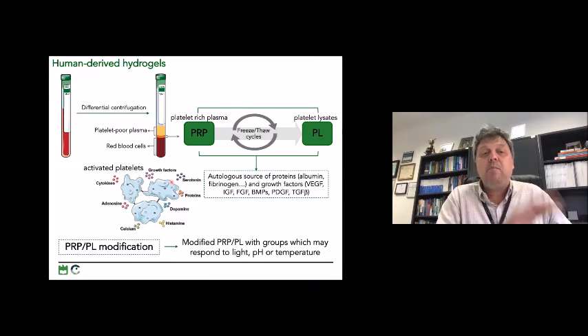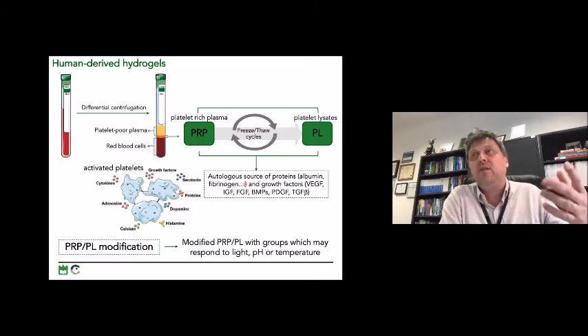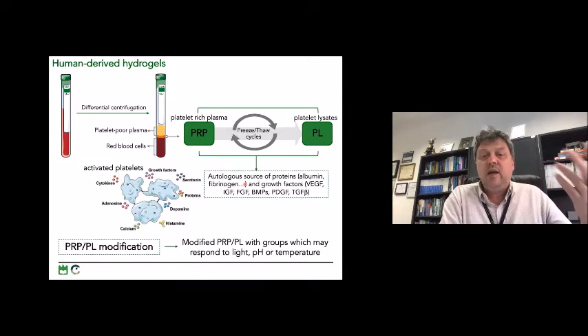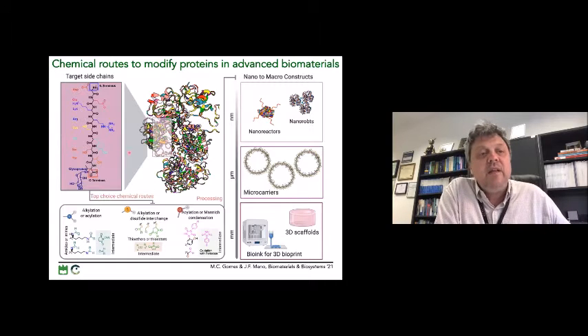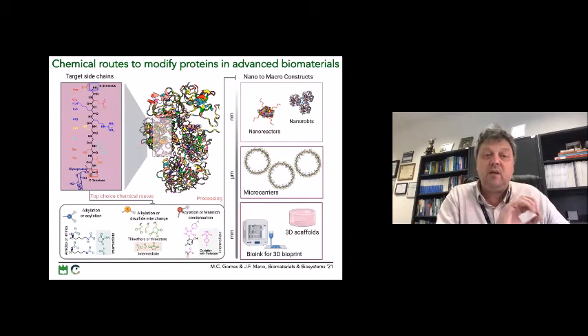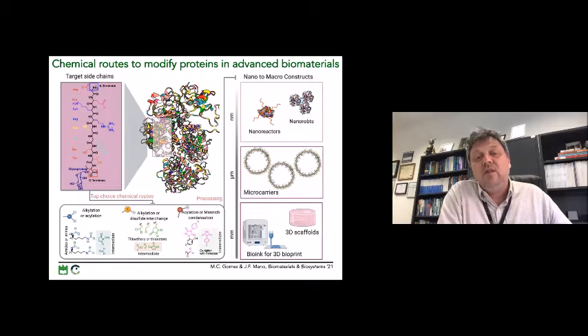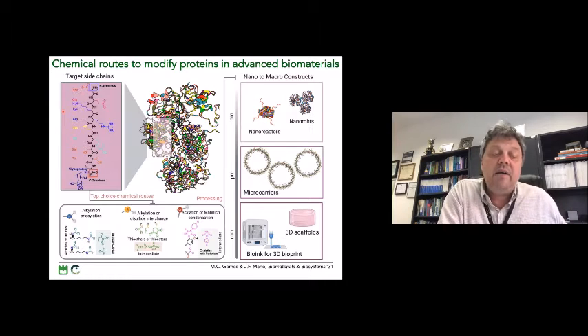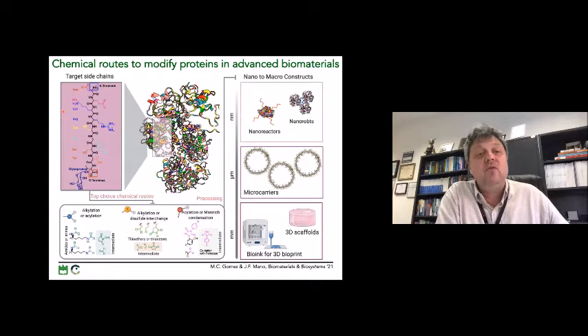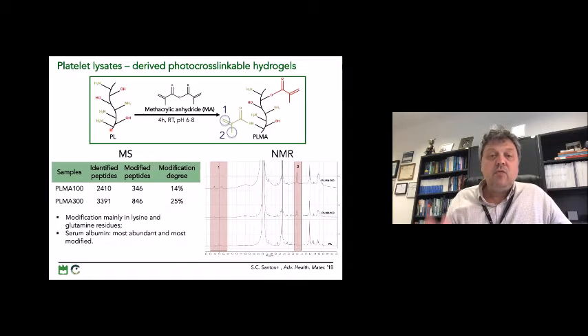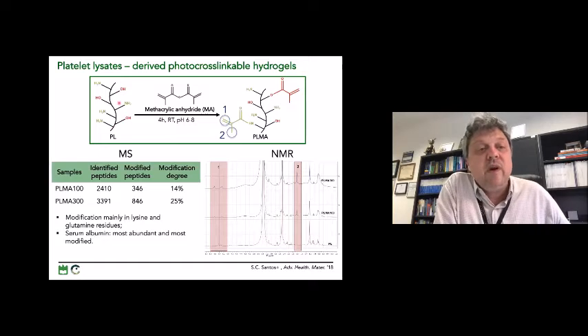So we hypothesize that by chemically modifying such proteins, we could produce biomaterials that could, for example, respond to light or to other external stimuli, for example, to generate hydrogels on demand. In general, it has been recognized that proteins may be chemically modified, either more specifically in terms of the site where we want to do that, or broadly, using different types of chemistry. I'm not going into detail, you can see some examples, because they exhibit very interesting groups like thiols, carboxylic groups, hydroxyl, amine. And we can do a lot of modifications.